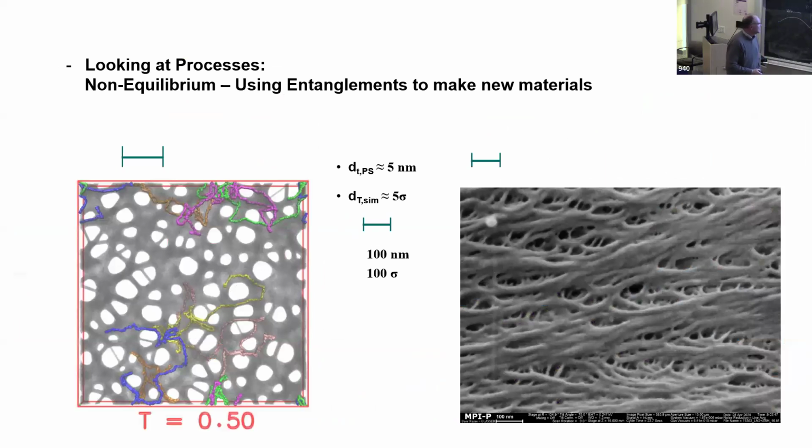However, when I take this situation here, you see that these chains expand over many such holes. Taking this situation, I would expect that you need at least about a third of this chain length. In the case of polystyrene, that would mean somewhere between 300,000 and 400,000. We are now trying to get some long-chain polycarbonate, which would have many advantages also from a technological point of view. But I learned that besides somewhere in a drawer from the 60s at Bayer, there is no long-chain polycarbonate available. So this is all based on linear chains.